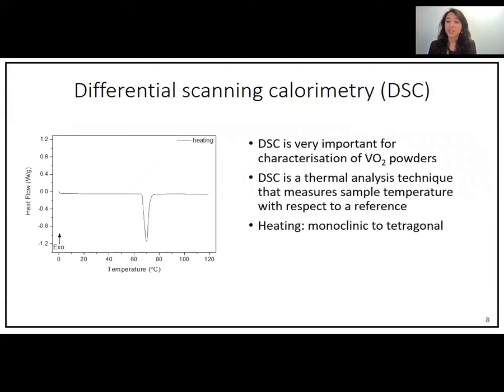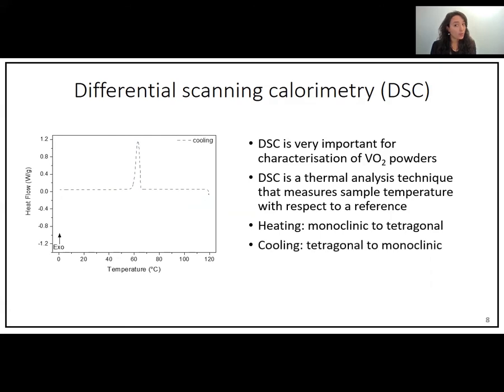Differential scanning calorimetry is one of the most important and most used characterization techniques for vanadium dioxide powders. DSC is a thermal analysis technique which measures the difference in the amount of heat required to increase the temperature of the sample with respect to a reference. When VO2 is heated, an endothermic peak is visible as energy is absorbed to change the structure from monoclinic to tetragonal. On the other hand, when the material is cooled down, energy is released, therefore resulting in an exothermic peak. The peak temperatures are often used to indicate the critical switching temperature of the material.